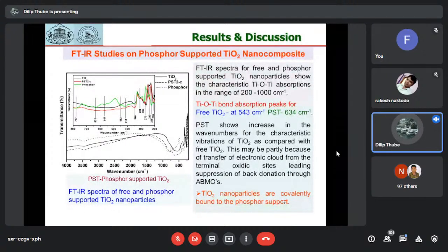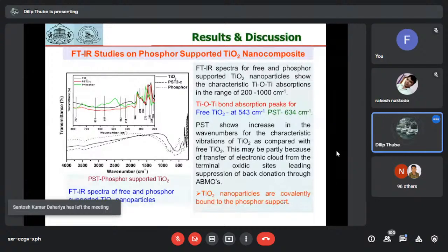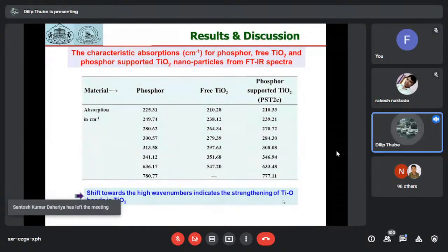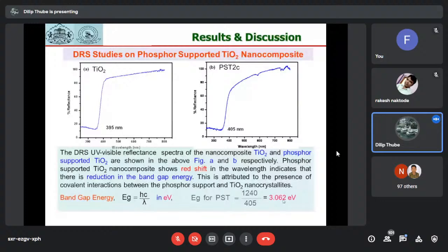So the inference is that TiO2 nanoparticles are covalently bonded to the phosphor support material. This is also observed in the UV visible spectra of all these materials. There is a red shift in the wavelength, which indicates that the band gap is reduced. One of the important expectations we have kept during the project is that we want material with the reduced band gap. So due to the use of phosphor support, the band gap is reduced, as well as TiO2 nanoparticles are chemically bonded on the surface of the material.